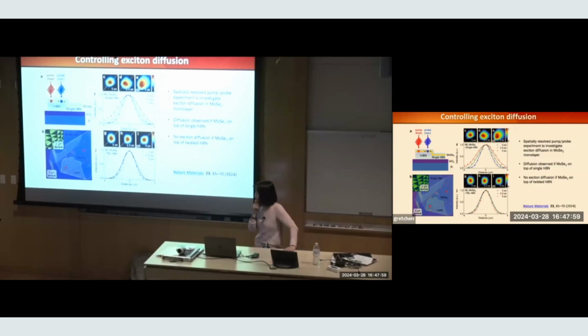How do you know where the extra carrier is spatially? Right, so you monitor how they behave when you apply a vertical electrical field. That helps you know where they were initially. Depending on the electrical field, the electron and hole will move in a very definite way. You see how your spectrum evolves. And of course you can start with a DFT calculation as a guess, and then you watch how these resonances evolve with electrical field.